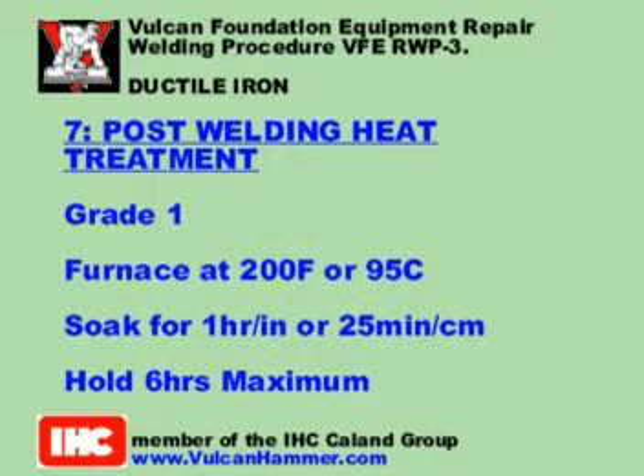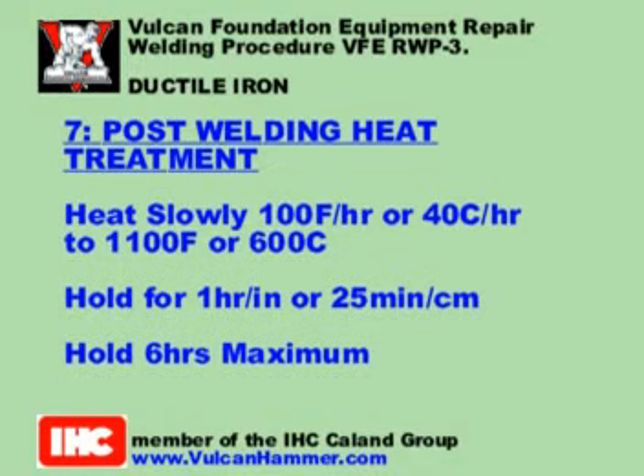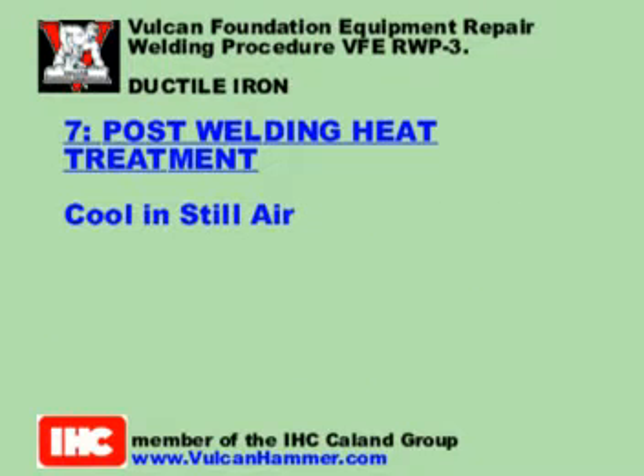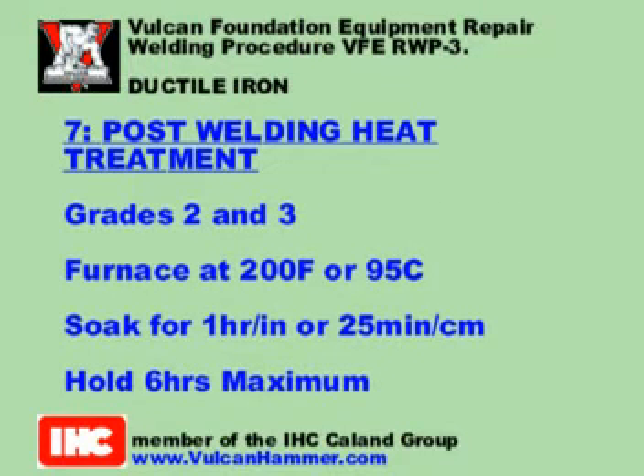Grade 1. Place in a furnace at 200 Fahrenheit or 95 Celsius and soak for 1 hour per inch or 25 minutes per centimeter, 6 hours maximum. Heat slowly at 100 Fahrenheit per hour or 40 Celsius per hour to 1100 Fahrenheit or 600 Celsius and hold 1 hour per inch or 25 minutes per centimeter, 6 hours maximum. Cool in still air.